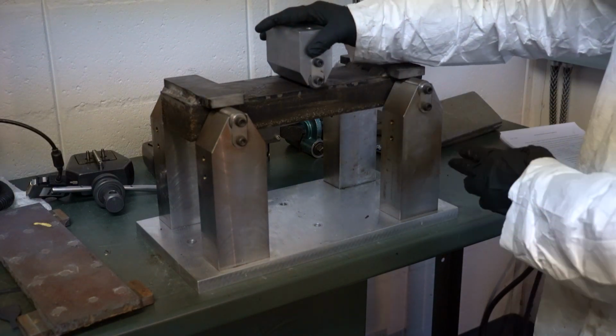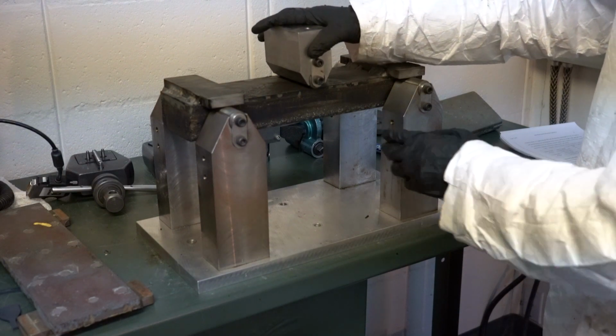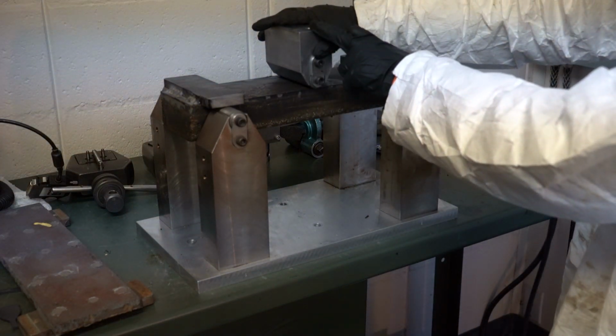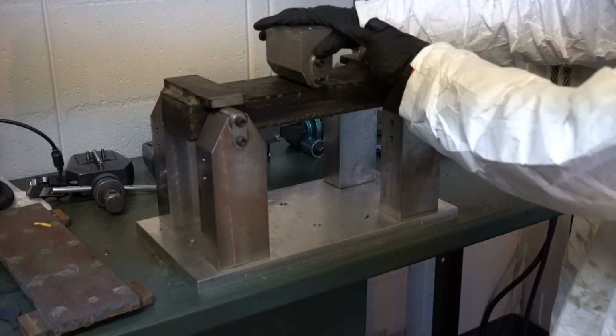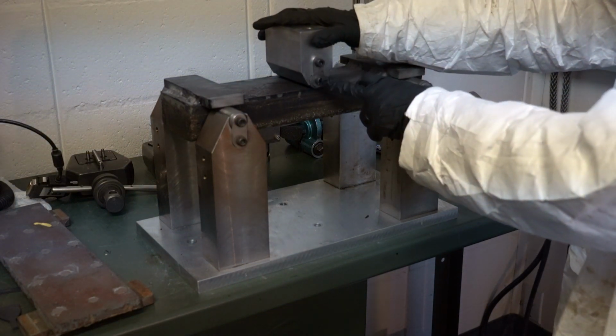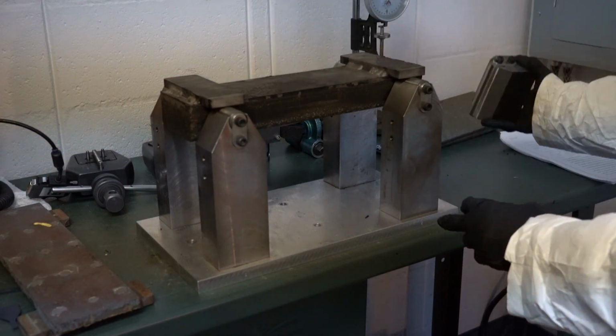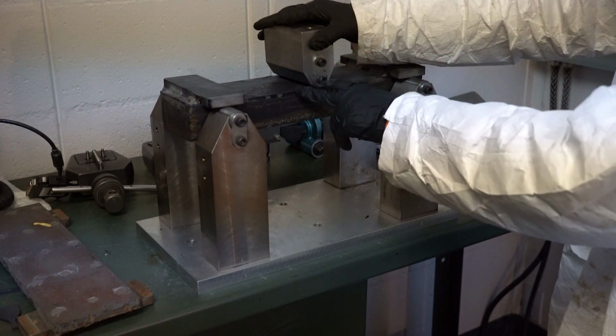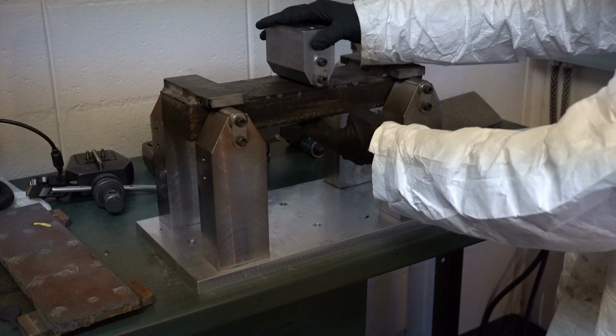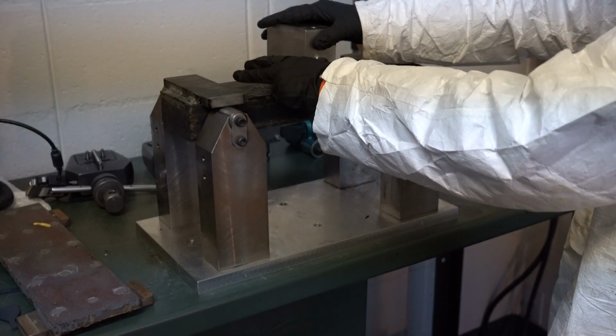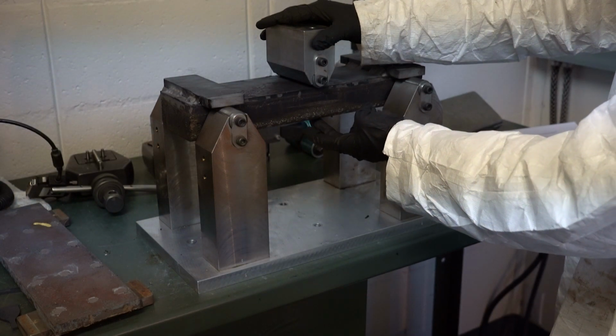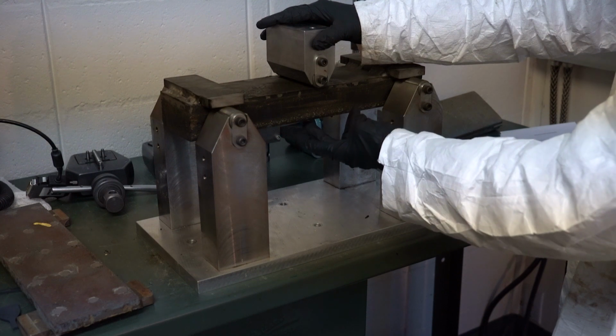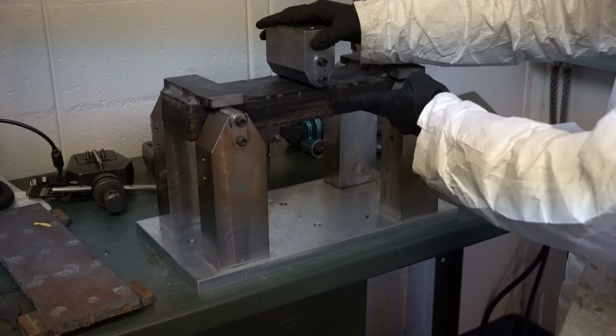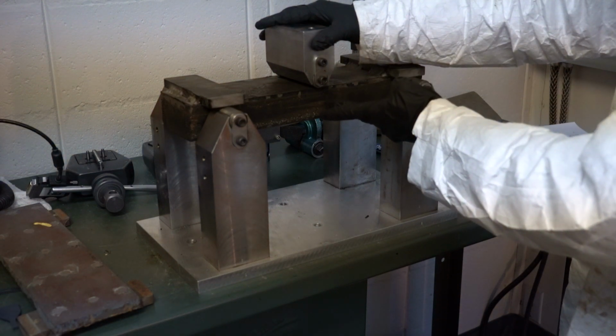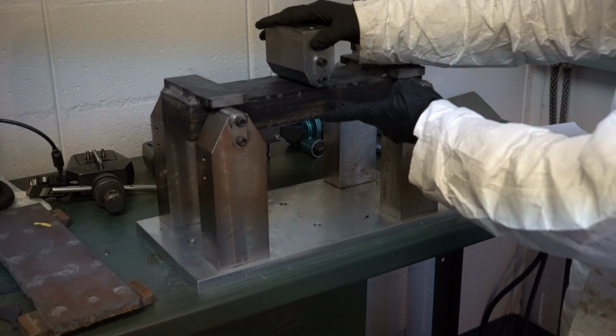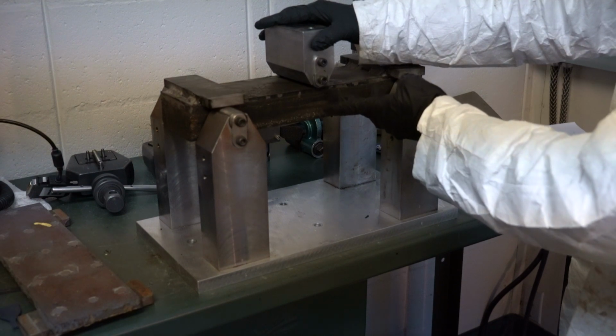This is the 3-point bending fatigue test, and it gives a compression from 5 kilonewton all the way up to about 7 kilonewton until failure. It takes weeks to finish the test sometimes, and it gives a compression on the top flange and a tension at the bottom. So for this purpose, it's steel plate on top and the epoxy asphalt concrete at the bottom. This test evaluates the tensile property of the epoxy asphalt overlay, and simulates the real deflection caused by heavy load traffic on a bridge deck.